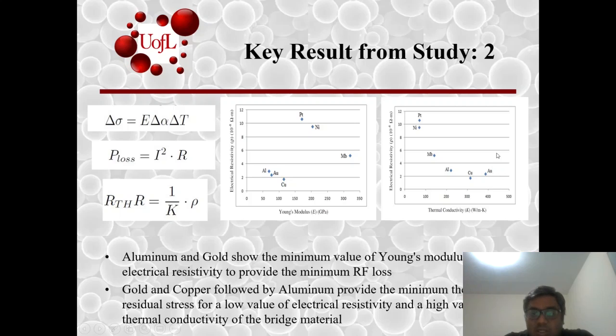which have higher thermal conductivity, they mentioned that gold and the copper followed by the aluminum provide the minimum thermal residual stress because they have the low electric resistivity and also high value of the thermal conductivity. So they concluded that the gold and the aluminum both can be the best candidate materials for the bridge material.